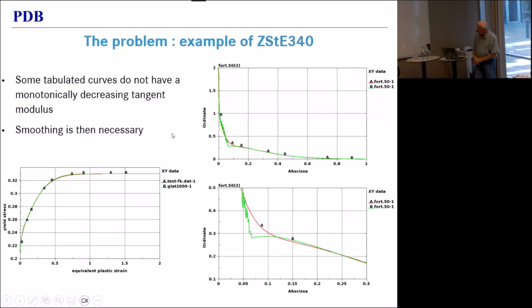If you actually look at the derivative, you see that in the right upper corner, and you see a zoom in the lower right corner. You see that the original tangent was not even monotonically decreasing. We had some oscillations here and a slight increase. And with the smoothed version of the yield curve, that pathological behavior disappeared.